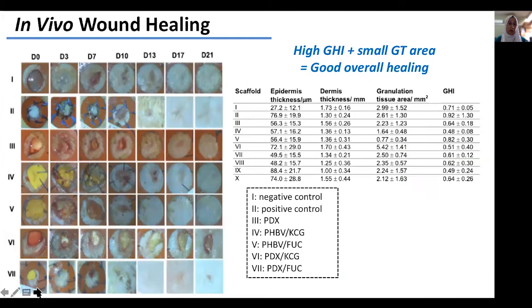Therefore, to test our hypothesis, we performed in vivo wound healing studies where we compared the performance of different seaweed-containing scaffolds over different time periods. So the wound healing study was carried out over 21 days, and we took photos of how the wounds were closing over time for the different scaffold groups. Scaffold 1 corresponds to the negative control and scaffold 2 corresponds to the positive control.